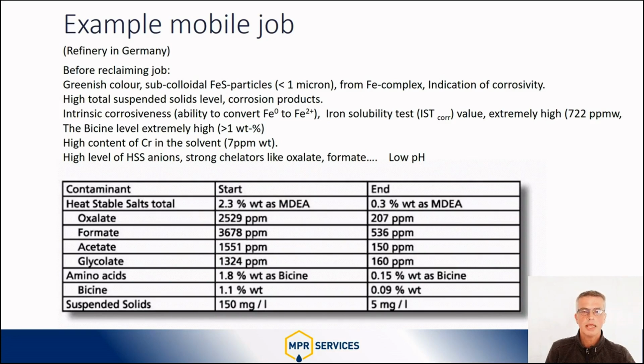The complete reclaiming job took less than a week, and as you can see in the table, the heat stable salts and amino acids were greatly reduced to below most of the common guidelines in the industry. For example, 1000 ppm for formate. The color became rather white, and already on the job the suspended solids level was much lower. The iron solubility was reduced from an extremely high level of 722 ppm to below 20 ppm.